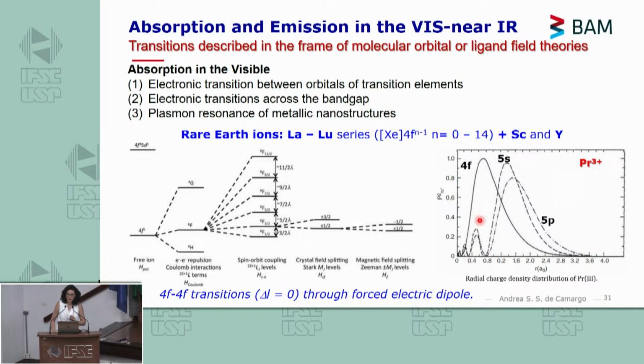Another interesting thing about these trivalent ions is that the 4f optically active orbital here is internal to 5s and 5p, where the bonding actually occurs. This means that the electric field caused by the ligands around the atom influences very little the energy structure of the levels, okay? Because the transitions happen internally in 4f orbitals. And this is a distribution of the radial probability of the orbitals here. And you can see that 4f is more internal, whereas 5s, 5p, 6s are more external. So this is important to keep in mind.